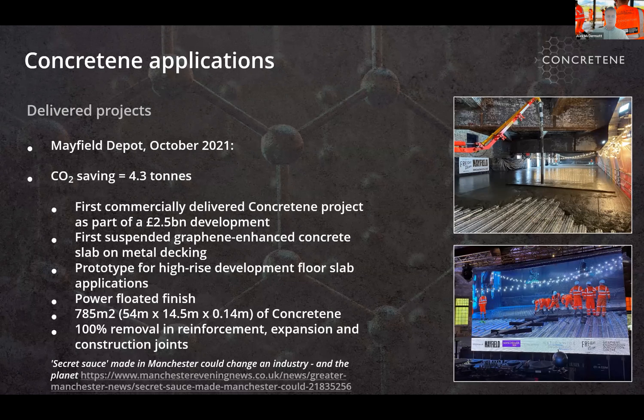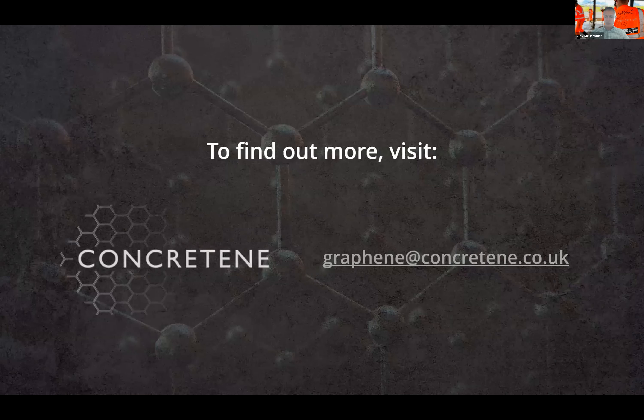The final project is Mayfield Depot — the old goods railway station next to Manchester Piccadilly. This is a composite deck approximately three metres off the ground, 54 metres long and 14.5 metres wide, creating an event space. We eliminated reinforcement and joints; we couldn't thin it down further as the concrete depth above the rib is only 73 millimetres. It was a great opportunity to take the technology off the ground and into a different application as we develop the material for higher-rise development. We calculated a saving of 4.3 tonnes of CO2 on this application. That was a quick snapshot of Concretene — I hope that was helpful and invites questions.